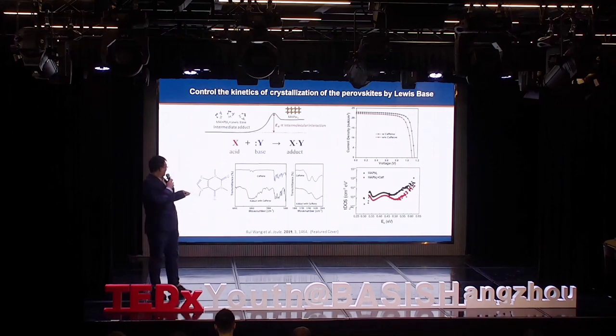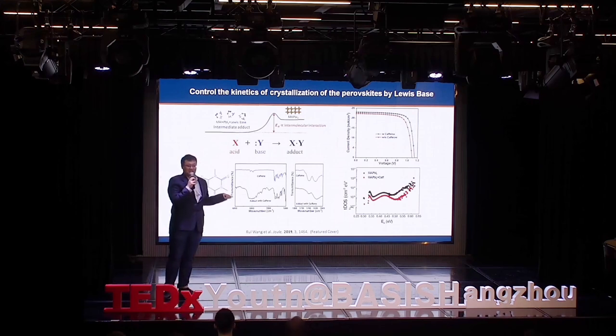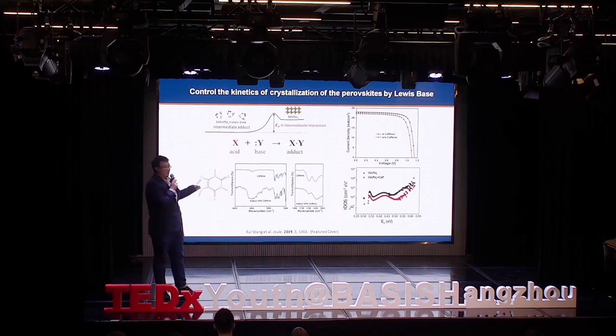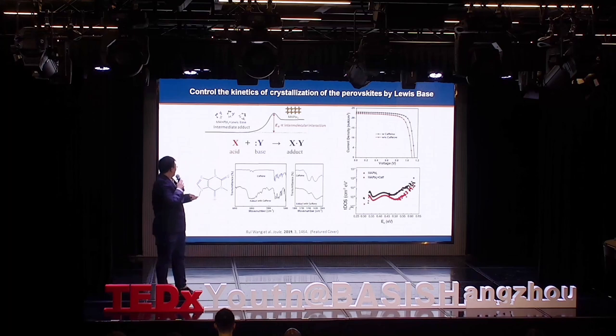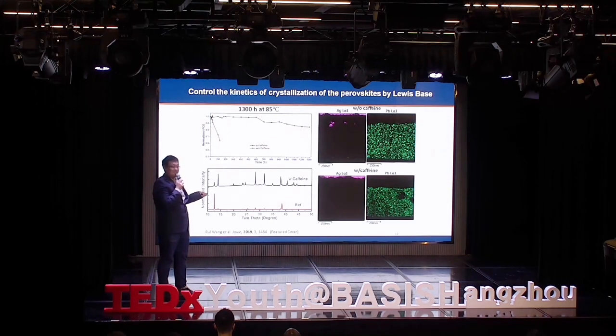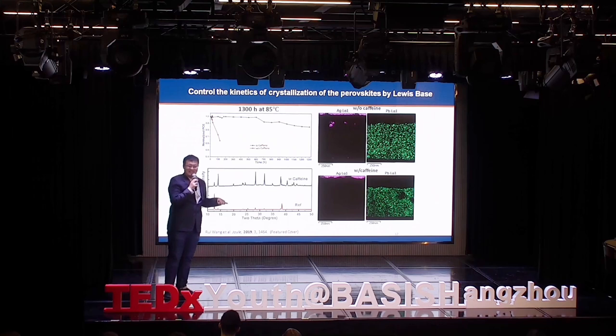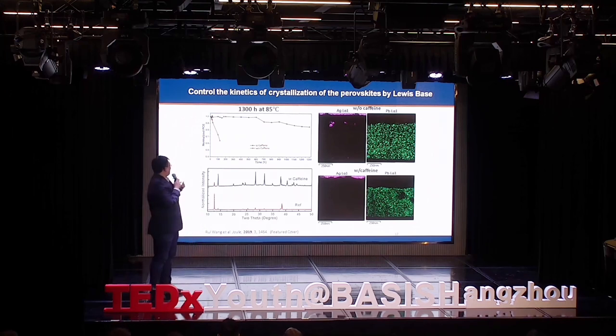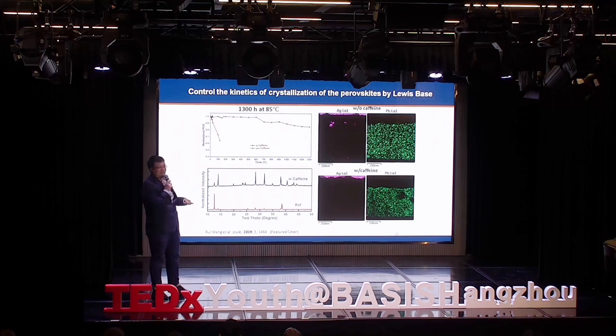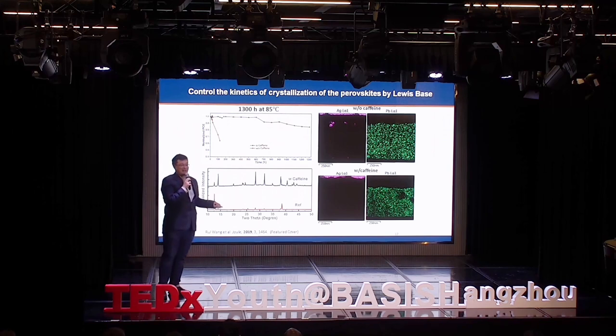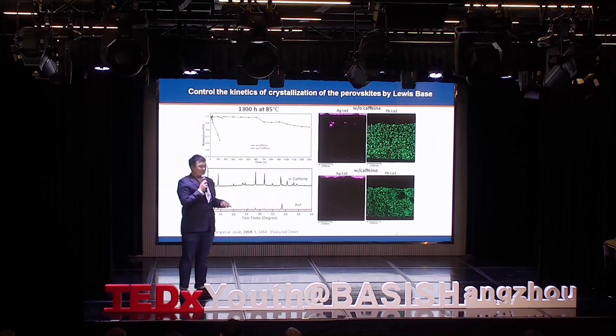Very excitingly, caffeine contains a functional group that we had already proved could stabilize perovskite solar cells. So we mixed caffeine into the perovskite, and excitedly found that the efficiency increased a lot. We baked the solar cell at 85°C — actually 85°C is the standardized measurement temperature for solar cells. After adding caffeine, the efficiency and stability increased a lot, and the cells were still alive over thousands of hours. Sometimes thinking outside the box makes your research exciting and interesting, and you will enjoy it.